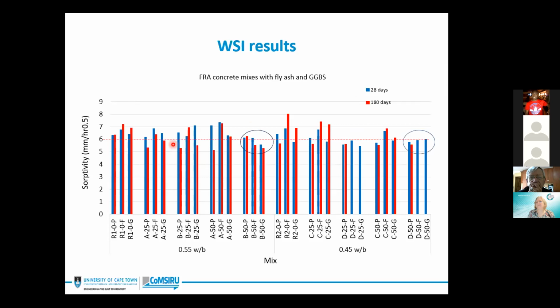Now, this is a graph that contains all of our mixes, including GGBS and fly ash. And from this graph, we can see that at 50% FRA content, the concrete mixes show better sorptivity values.